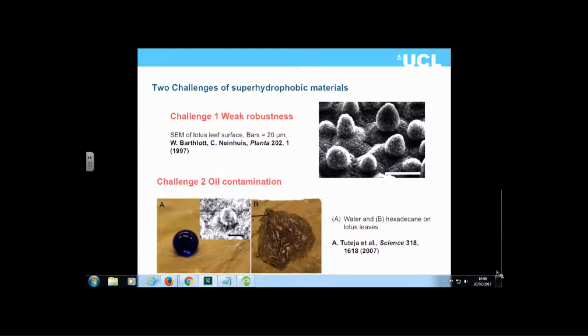Another problem is oil contamination on the surface. If the surface gets contaminated with oil, it doesn't then behave as a superhydrophobic material. And so these are some of the two main challenges in the area in terms of commercialization.